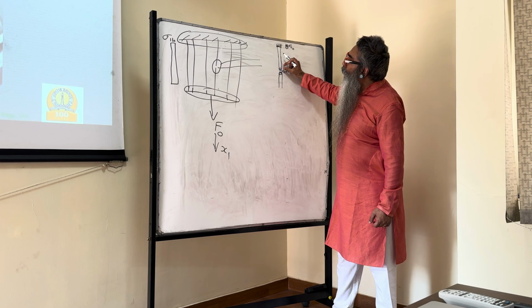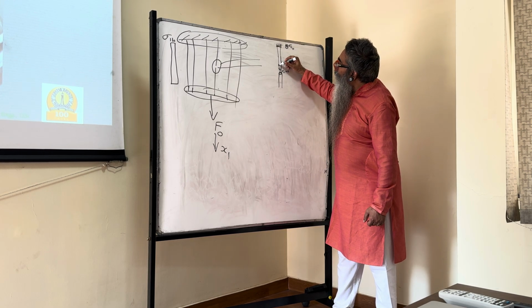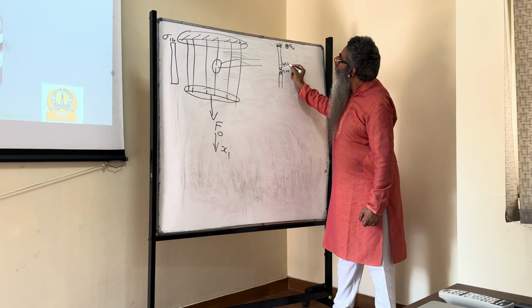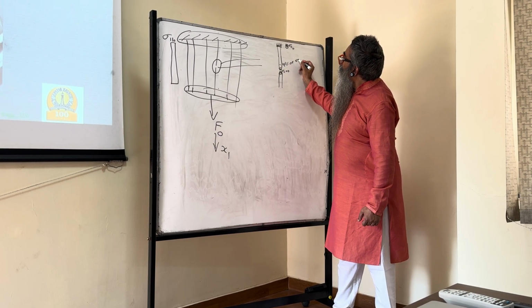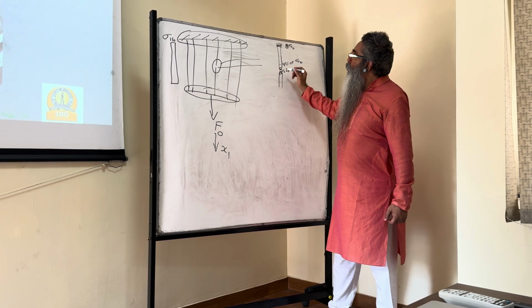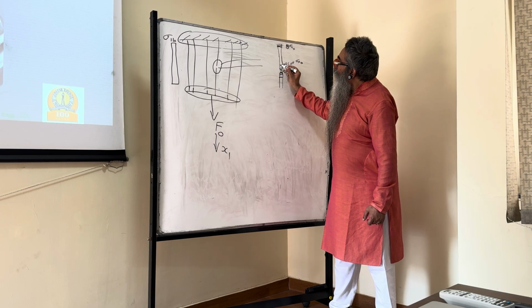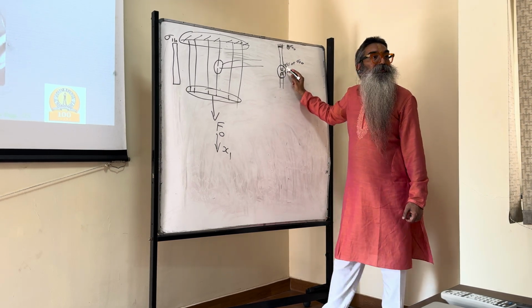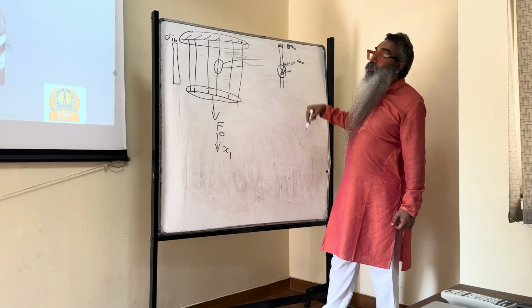So just about 10 microns into it, you will see that 99% of sigma 11 naught is already reached. So same thing with this. So it's only a very, very small portion of the fiber which has become ineffective. Most of the fiber remains.